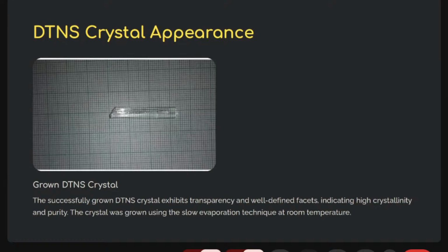So this is the DTNS crystal we got after the slow evaporation process over 60 days. We got this crystal over 60 days. As you can see, this is much bigger in length. So we can say that from the slow evaporation process we can get good quality crystals.